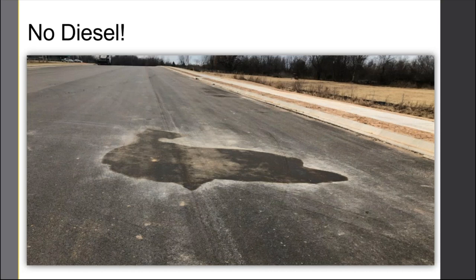Make sure you're keeping the truck clean, but use an approved solvent — no diesel. Diesel is not an approved material for cleaning. It is a lighter cut of petroleum, same as asphalt, and it will actually eat the asphalt off the rocks. This is an example of where that did happen — a diesel spill did start to disintegrate part of the mix. That section had to be cut out and replaced.